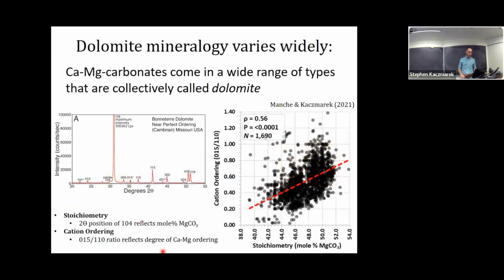So here's what we've learned by studying a lot of dolomites. We know that the degree of cation ordering and the composition vary widely. What we do is go into these X-ray diffraction patterns and measure two things. One, we measure the position of this 104 peak, and it shifts based on the amount of calcium and magnesium in the mineral structure. Magnesium is a smaller cation than calcium, so the more calcium you have relative to magnesium pushes the position of this 104 peak, and actually the whole pattern, generally to the left.